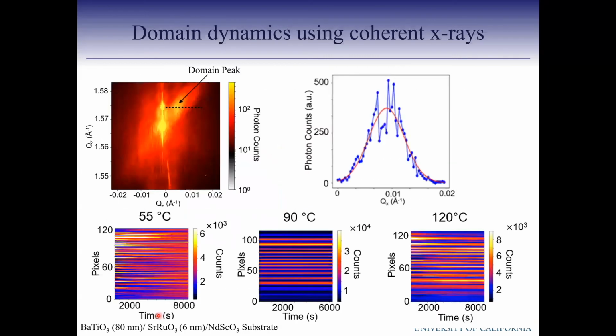Two things will define your time scale. One is your detector frame rate, how fast your detector can capture the pattern. Now we have detectors which are down to about 0.1 millisecond, so you can get to that. However, once you get to 0.1 millisecond, your sample should be able to give you enough photons to see something. Usually when you collect data, you average to get some SNR. But if you have a strongly scattering sample, which within 1 millisecond would give you enough photons to do these kinds of analysis, then you can measure those timescales.